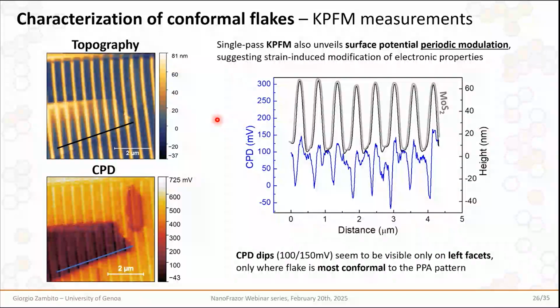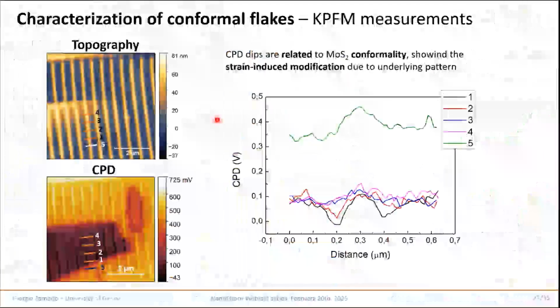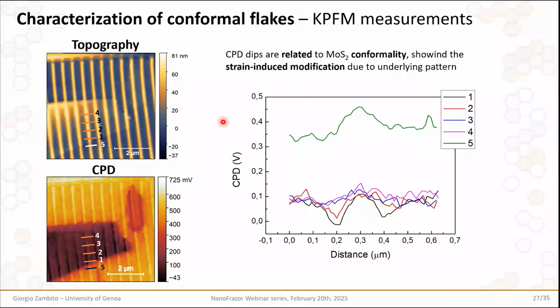The fact that this is a strain-related effect is also visible from this line profile comparison of CPD, where we compare line profiles of CPD extrapolated from regions that possess different degrees of conformality. And we see that these CPD dips are present only in the regions that are most conformal to the PPA facets, while they are basically absent if we consider regions where the flake is basically freestanding on top of the facets, like profile number 5 here.